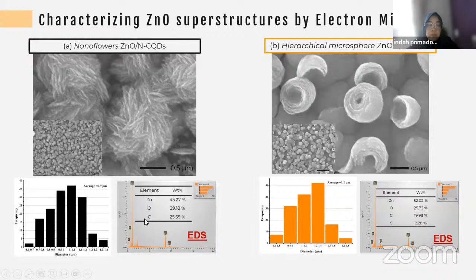After the EDS experiment, you can see of course there is zinc element and oxygen and also carbon. And I don't know why, because the carbon quantum dot contains organic elements like carbon, oxygen, hydrogen, and also nitrogen, because here we add some urea. But of course, hydrogen cannot be analyzed by EDS, it's too small. But nitrogen, I don't know why it cannot be detected here. Maybe the concentration is very small.